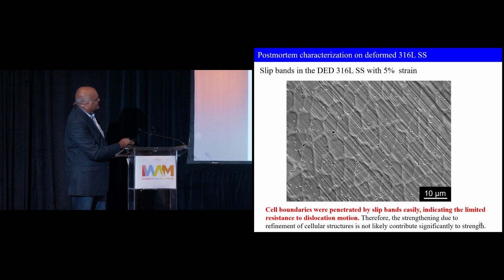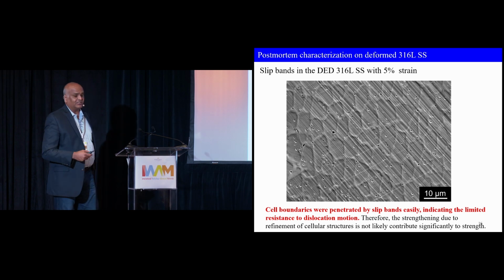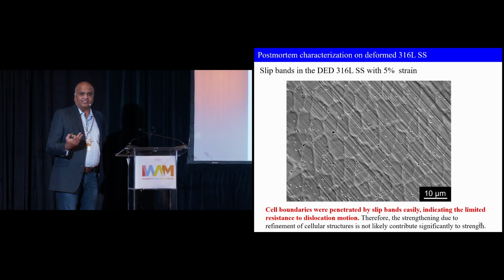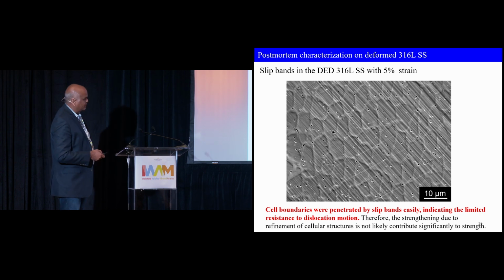But what you can see is the slip traces, and you can see these cutting all the cell boundaries. So really the cell boundaries don't stop dislocations like red traffic lights that grain boundaries do. So treating them as grain boundaries is not correct.